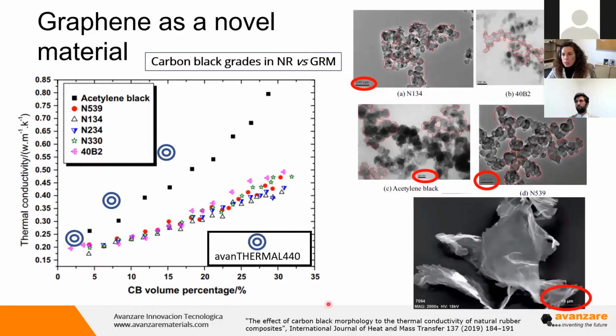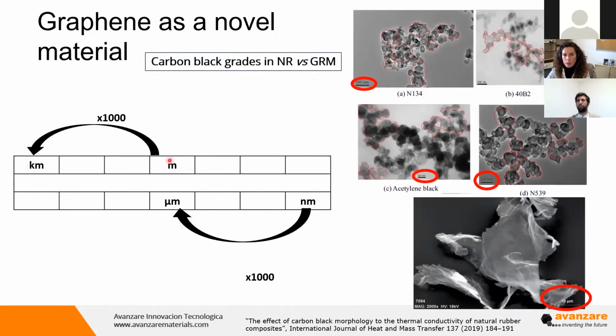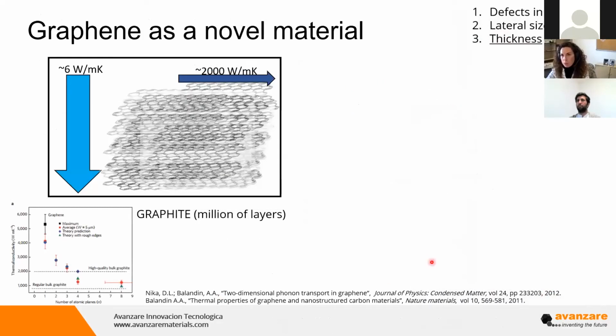We can explain this because this kind of material is about 40 microns in lateral size, while this one is less than 50 nanometers, and even the aggregates have a smaller lateral size. So it is like comparing a meter to a kilometer; it's the same range as from nanometer to micrometer. The third important aspect to take into account is the thickness of the material.